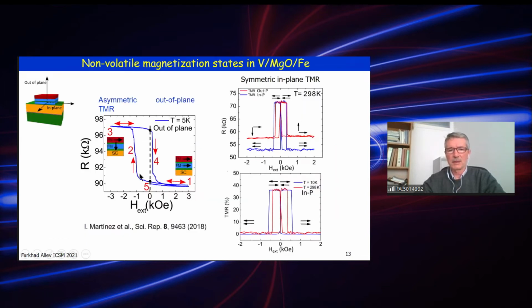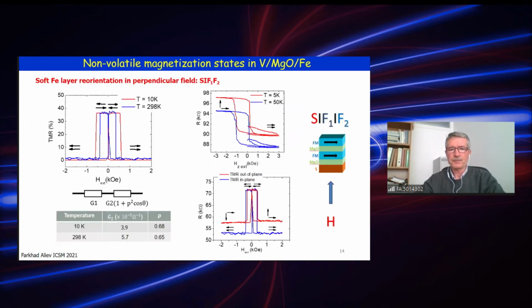This is out-of-plane magnetization tracked through tunneling magnetic resistance. We can enter a perpendicular magnetic state, sweep the field, and keep the system out-of-plane magnetized at low temperatures. While at room temperature, we don't have the non-volatile perpendicular state, but at low temperatures we do.